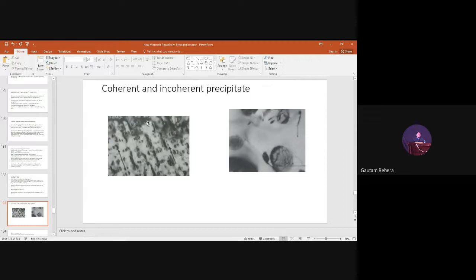So you can see this is an image showing coherent precipitate. You can see these are very small particles. But the interesting point here is, if this is the size of the particle, it is not exactly the size of the particle. It is appearing big, but the actual size of the particle is very small. Actually, this is a transmission electron micrograph, and this is an image of strain field.